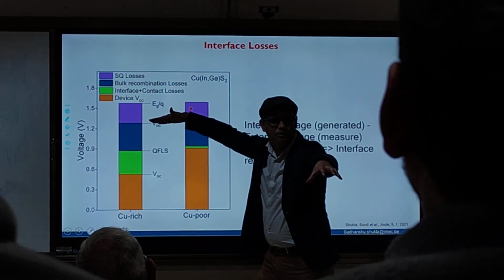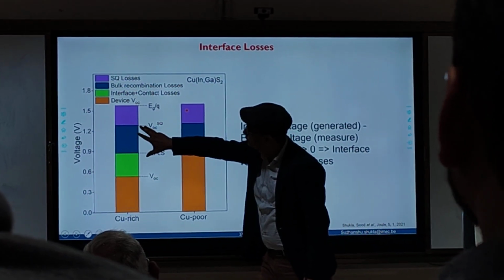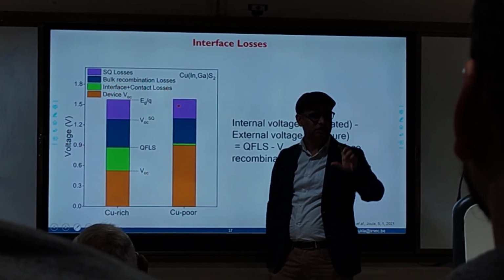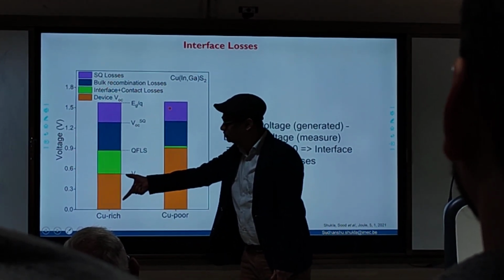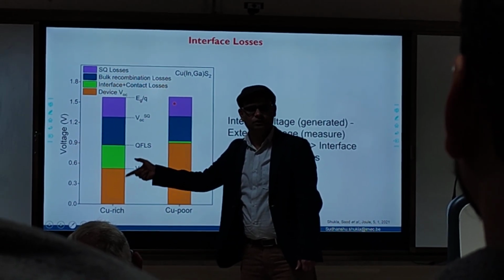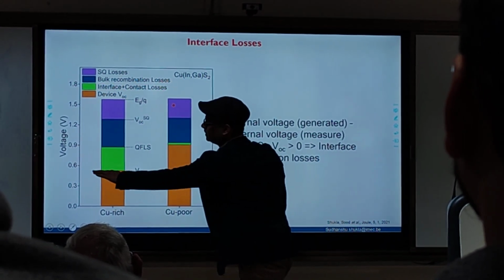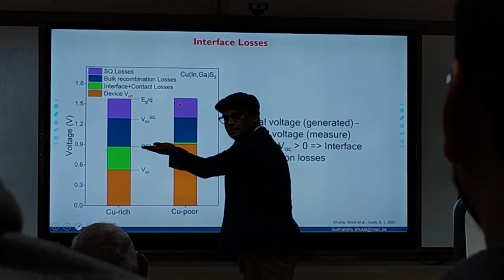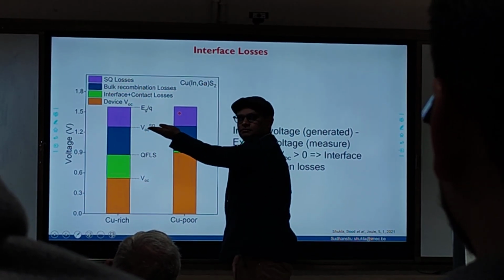While theoretically this is possible, which means this is a loss, it's called interface loss because this is a bulk measurement and this is the VOC that you measure. Okay, so there are a lot of losses. Eventually you get this number while you should be getting this, while the theoretical limit is this.